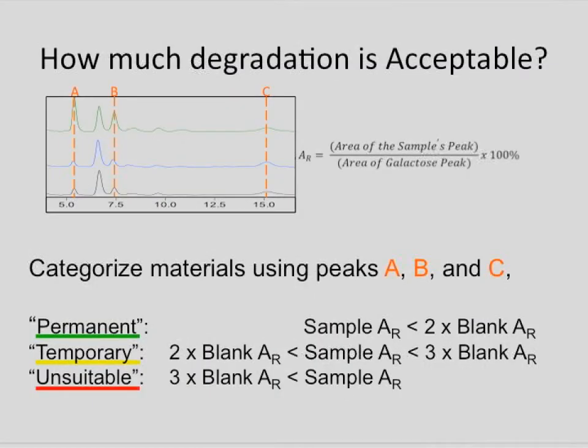So how do we do our assessment in a more controlled way? We've decided to always inject an internal standard. We use galactose, and then we also put cellobiose, which comes in out here somewhere. We typically look at these three peaks, A, B, and C.